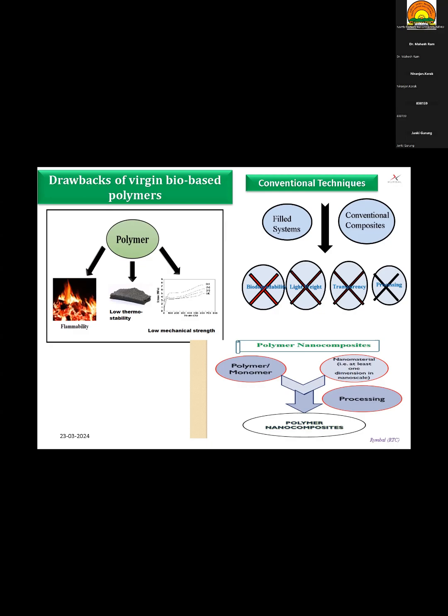Thus, even though this was used for a long time, more than 50 or 60 years or so, now a new concept is coming into the picture, and that is with the help of nanomaterial or nanostructured material. So if you can incorporate a little amount of nano reinforcing agent, where the conventional system required 50 to 60 parts per 100, it requires 0.01 to a maximum of 5 weight% nanomaterial, and a suitable combination of nanomaterial with the polymer results in a polymer nanocomposite, which has great significance over the conventional filled or composite system.